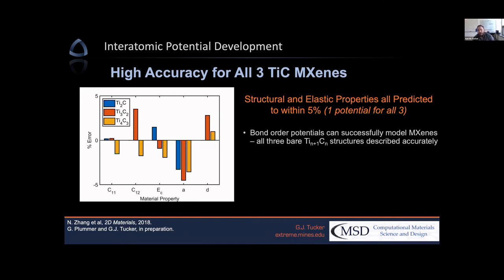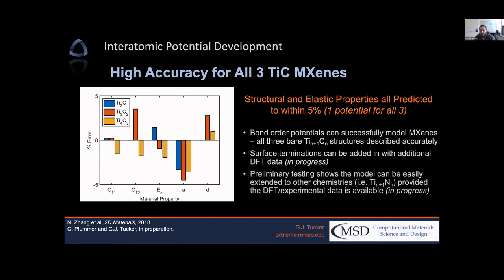In summary, for this potential part, bond order potentials can successfully model MXenes, and all three bare titanium carbon structures for the time being. The surface terminations can now be added in with additional DFT data that we can get, and this is actually in progress right now. We'll have various surface terminations in this potential. Now that the numerical optimization algorithm is completed, it's very easy to tune it for a specific type of system that we're interested in. Lastly, preliminary tests show that the model can easily be extended to other chemistries, such as the nitrides, other types of M-based elements or multi-M elements, provided that we have the DFT and experimental data available to optimize to. We are in the process of doing that and gathering that information from colleagues.